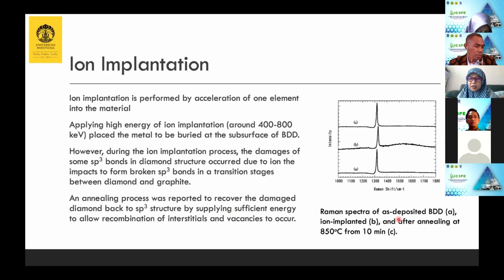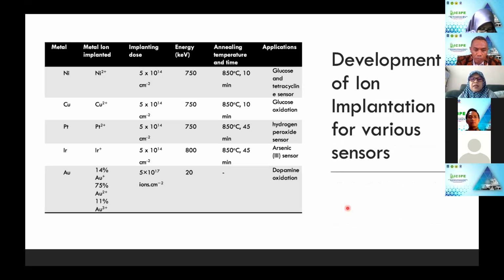Here we put annealing at 850 Celsius degrees for 10 minutes. And then this is some example of metal modification with implantation methods for sensors. We found some reports for glucose and tetracycline sensors, hydrogen peroxide, and also arsenic and dopamine.